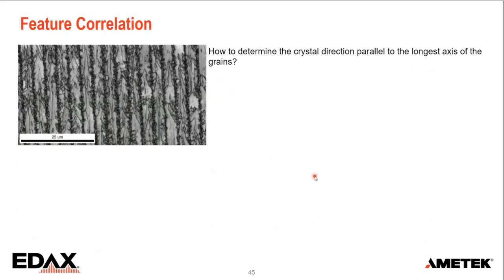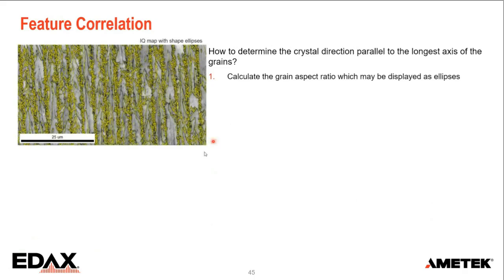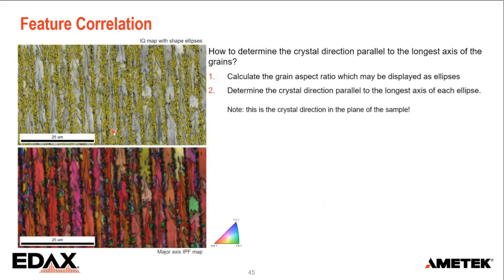So what we can do then is we can calculate the grain shape aspect ratio. We can show these very large or sometimes very small ellipses. And from these ellipses, we can identify the longest and shortest axis of the grain. And then we can quantify or identify the crystal direction parallel to the longest axis of the ellipse. And you can see that here in this image at the bottom. We call this a major axis IPF map.